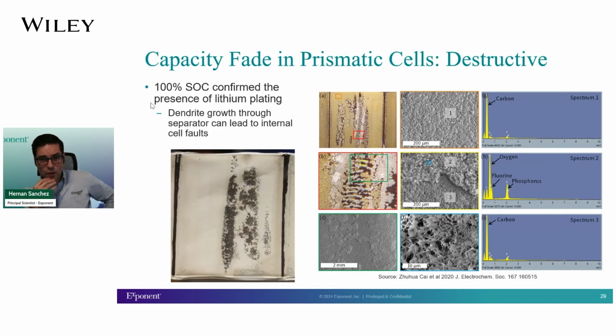And in this case, what we did was, once again, 100% cell teardown, air-free transfer, and because of the air-free transfer, we were able to see these dendrite-like features consistent with lithium plating and the growth of lithium dendrites on the surface of the separator. This is the separator mated to the negative, and this is on the negative, but that you can see in the image to the left, that's on the separator. You see those same features.